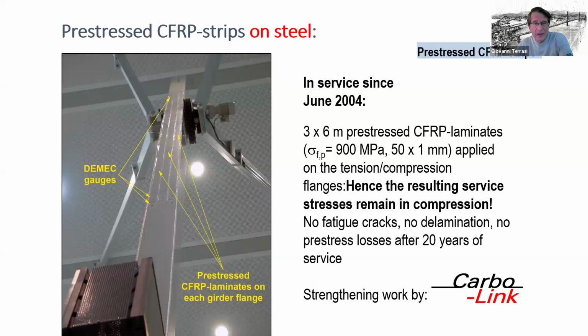And in fact, after 20 years of monitoring, my collaborators monitor this pendulum once a year, always in October. We inspect, and we had no more fatigue cracks, no delaminations of the pre-stressed Carbodur reinforcements, and no pre-stress losses, measured with strain gauges and DEMEC gauges, in particular at the end of the laminates, to observe any relative displacements of the anchored zones, which in fact were not present. We're just measuring temperature fluctuations caused by the difference in coefficient of thermal expansion of the CFRP and the steel. So this, I should say, is a very durable solution, and my last slide sums it up.